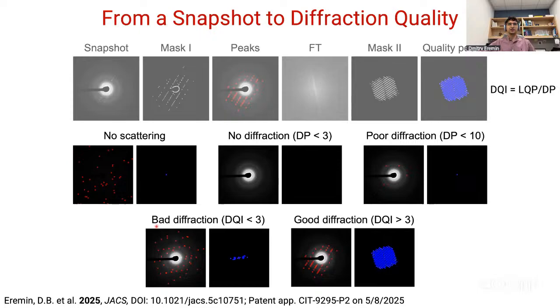Here you can see that, for this bad diffraction data, those who have experience with X-ray crystallography can clearly see this is just an overlap or superposition of 2 lattices. Ideally, both patterns here are pretty good. However, because we have a very low count of lattice quality peaks, the diffraction quality index is very low. So this pattern is never going to be selected for data collection. Whereas in this case, we have a tremendous number of lattice quality peaks and a very high diffraction quality index. Thus, a pattern like this will, or might, be selected for further data collection.